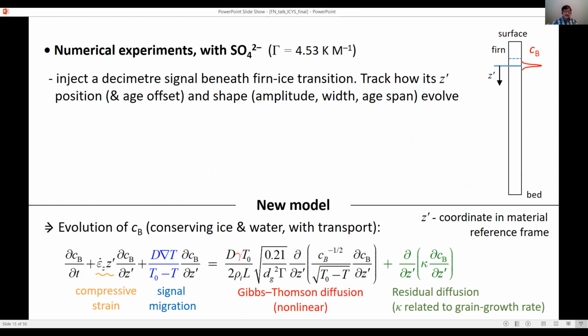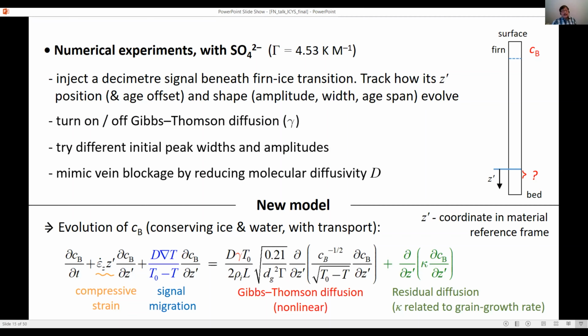So what we do now is to solve this equation in several experiments with just taking sulfate as our impurity, where we inject test signals just under the firn transition and then see what happens to them in position and shape. The Z prime here is the coordinate following the ice, if you're interested. Basically, whenever Z prime is positive, the signal is shifted from the ice. So I'm going to show you a few experiments turning on and off the Gibbs-Thomson term to see how that impacts Rempel's theory.